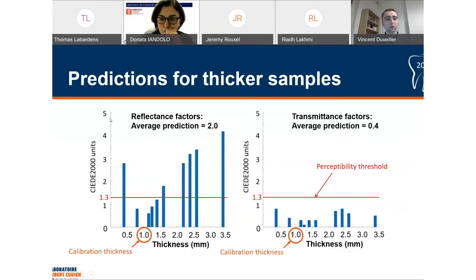Here is the result. Here you can see the color distance between the predictions and the measurements as a function of the thickness of the stack for the reflectance factors on the left and for the transmittance factors on the right. For the reflectance factors, the average prediction is 2 delta E units, so it's not great.